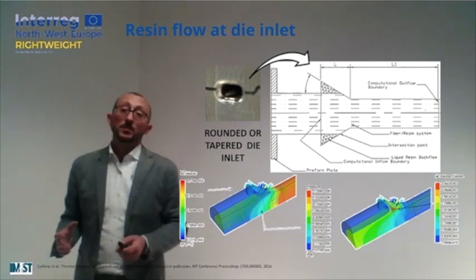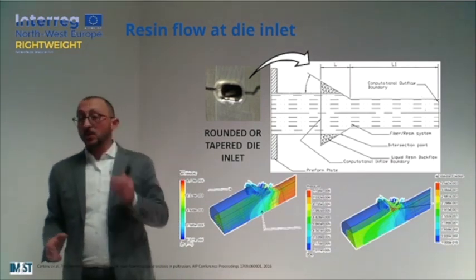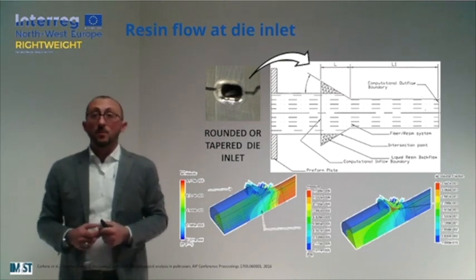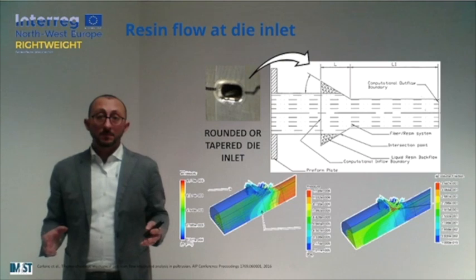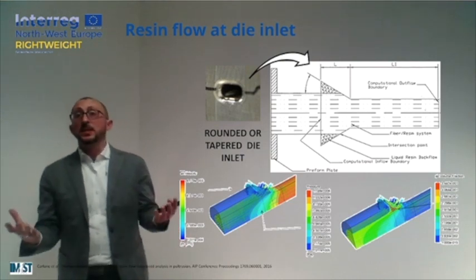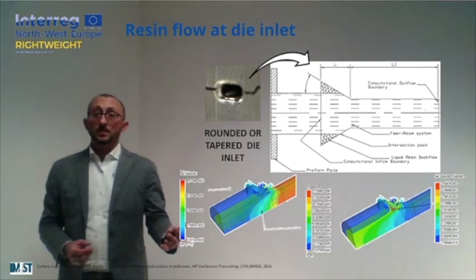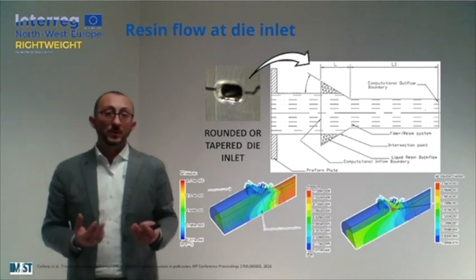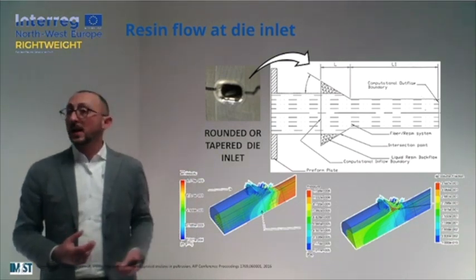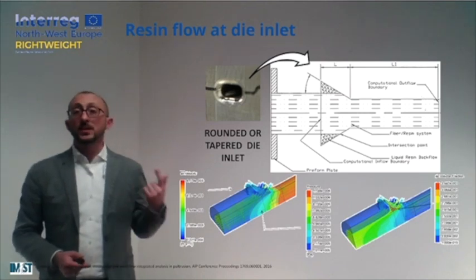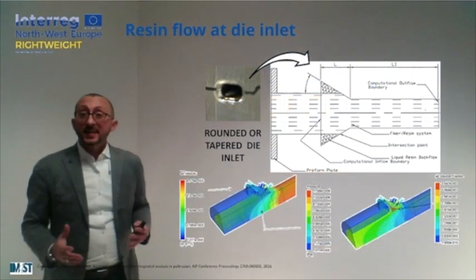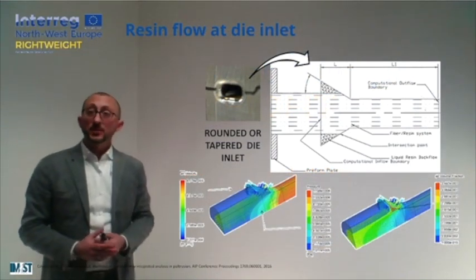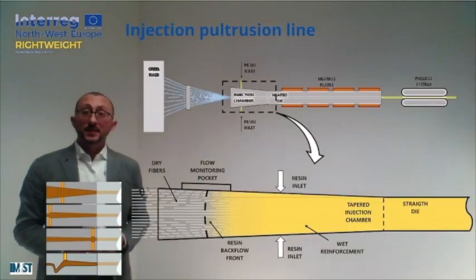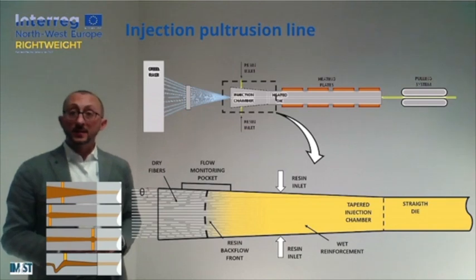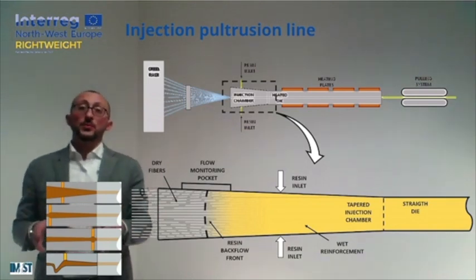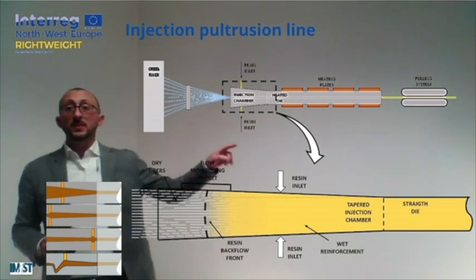This was quite an urgent problem some years ago, because if we look at the open bath, what we have there is a reactive toxic material that is releasing some volatile compounds in the surrounding environment. And we know that emissions from reactive resins are not really good for the environment and are not really healthy. As an alternative, the open bath configuration can be replaced by directly injecting the catalyzed resin inside the preliminary portion of our die, following a scheme that is depicted here.